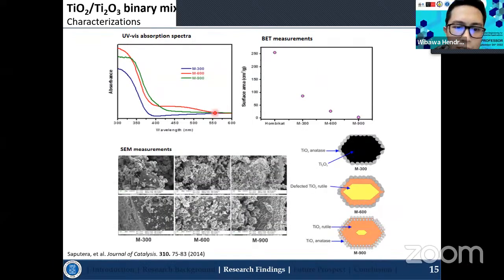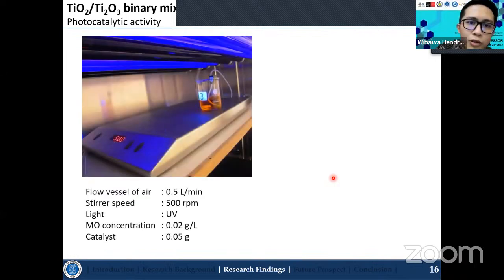And based on the scanning electron microscopy, it can also be seen that the defected titanium dioxide rutile is generated, where at 600 degrees C there is a mixture between the rutile and anatase, and there is also the titanium 3+ defect generated in this TiO2 system. And move on to the photocatalytic activity.